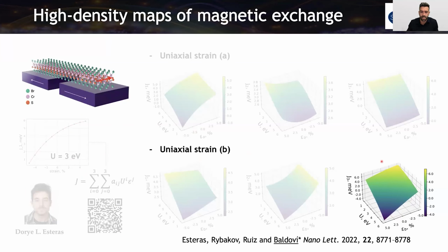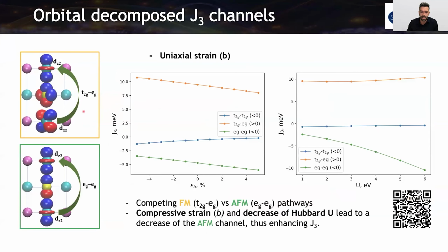Then we go to J3, which is connected with two atoms that are along the B axis, and in this case we have the opposite. This is a negative sign. This means a compression makes J3 increase, and there are two mechanisms mainly responsible for these interactions. In this case, this is the ferromagnetic mechanism from T2G to EG orbital, mediated by this sulfur atom. And in the case of the antiferromagnetic, it is EG-EG. With this compression, we are minimizing the antiferromagnetic pathway, diminishing it, and we are increasing the ferromagnetic character, the overlap here. So that's why we can increase J3 with this compression.